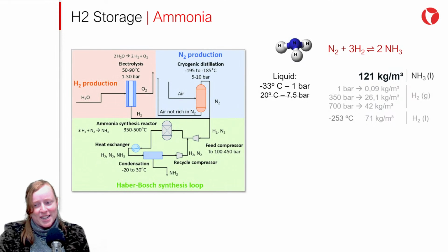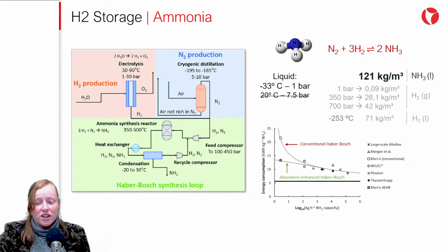Producing ammonia, however, is not free. The process starts by obtaining hydrogen through electrolysis and extracting nitrogen from the air through cryogenic distillation or by PSA. These 2 products are then combined in a process called Haber-Bosch process through a catalytic reaction at a temperature between 350 and 500 degrees Celsius. The energy consumption to produce ammonia is around 10 kilowatt-hours per kilogram of product. Once ammonia is obtained, its pure storage cost for periods longer than a few weeks will be much lower than that of liquid hydrogen or hydrogen compressed at very high pressures.